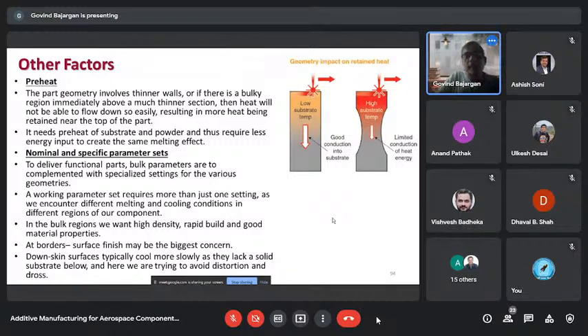There we may intentionally come up with a lower laser energy. So there is a global parameter and there is a local parameter. We have to come up with specific parameters for solving the local problems in a component. This also happens, and this is being done by all service providers, which in many cases we will not be aware of.